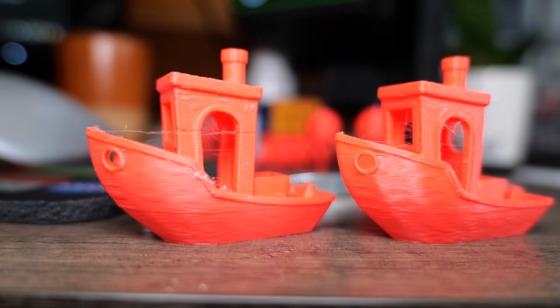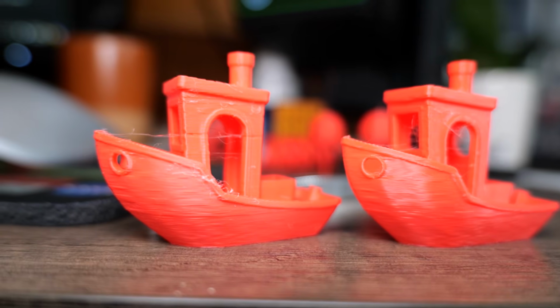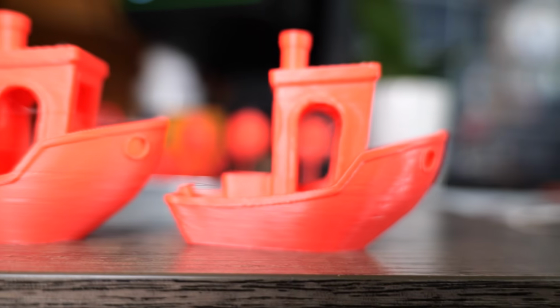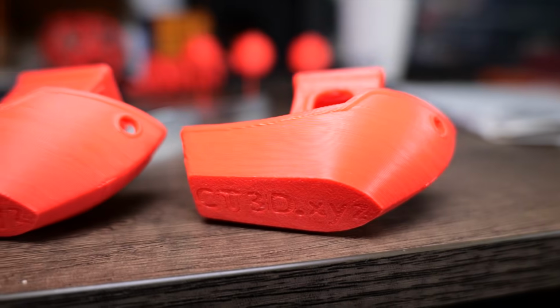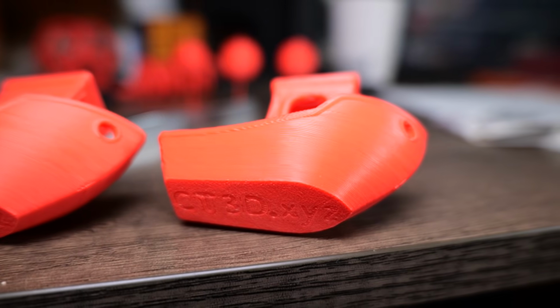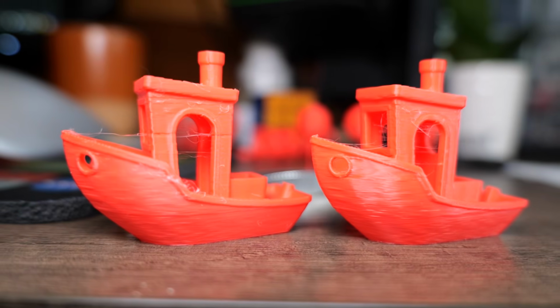And really the only thing you can see immediately is that the funnel doesn't look right. But upon closer inspection, you start to see a lot of things, like the gapping on top, you can see the concavity of the hole, you can kind of see the surface finish just doesn't really look that great, but amazingly a lot of the larger features don't look that bad at all without part cooling. So clearly, different features of these prints require different amounts of part cooling. The larger features need less cooling, and the smaller features need more part cooling. So we'd like to be able to tune our printer so that it cools less for when it needs less and cools more when it needs more.